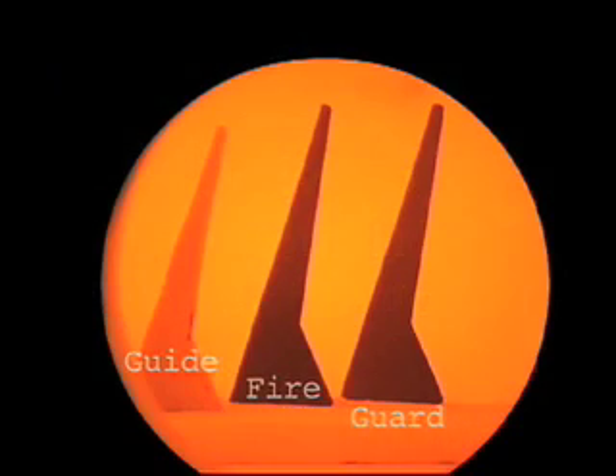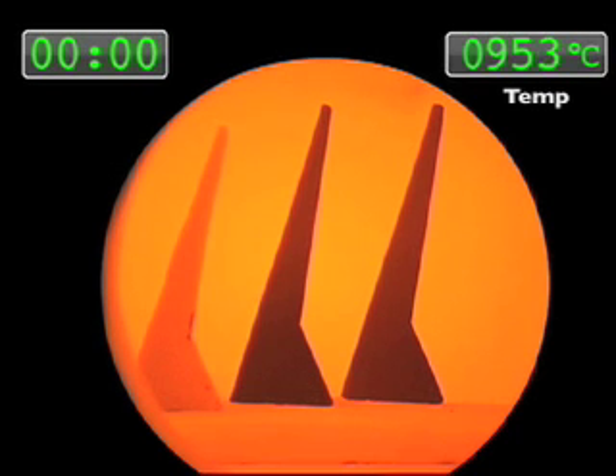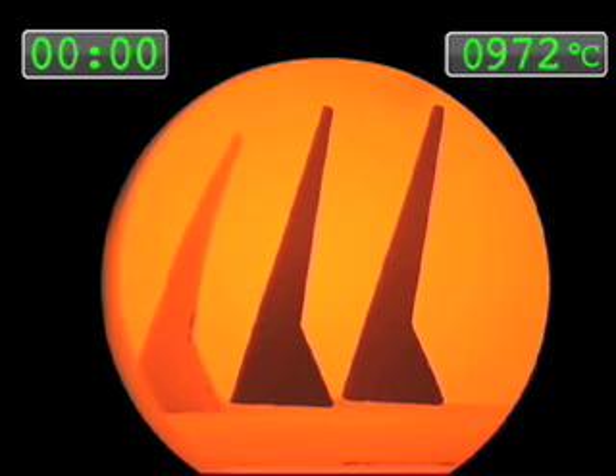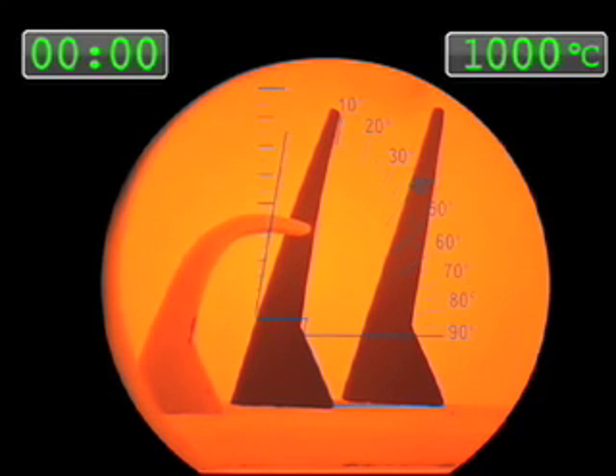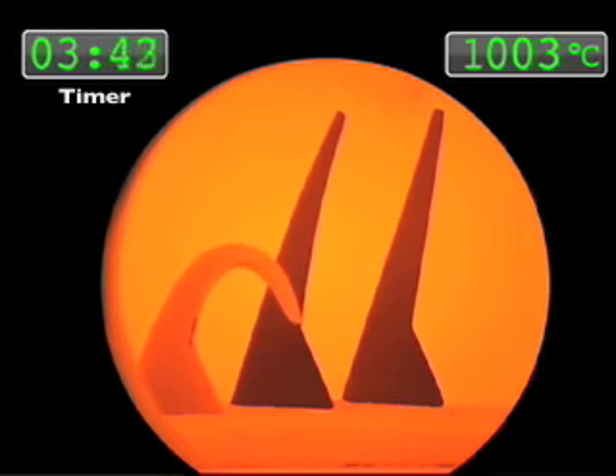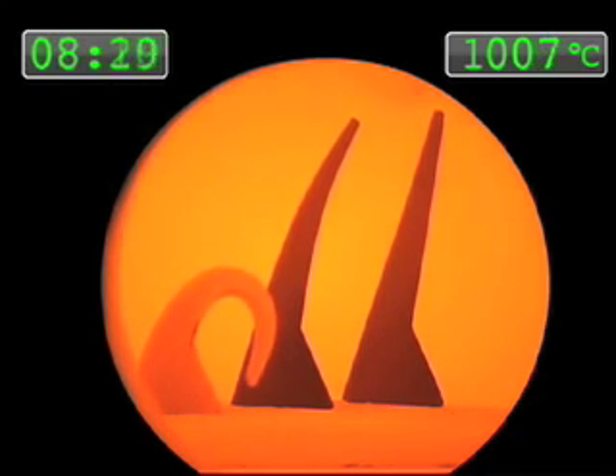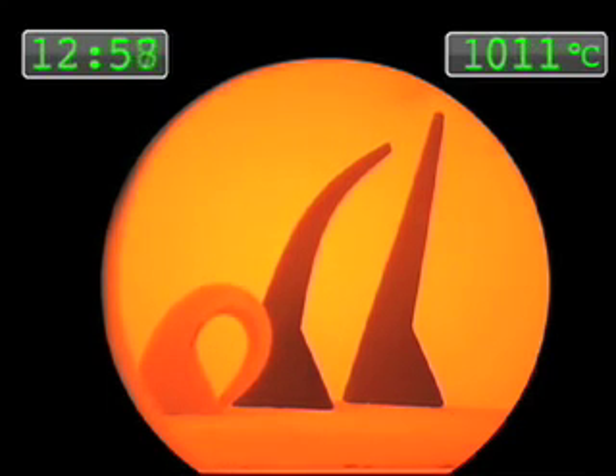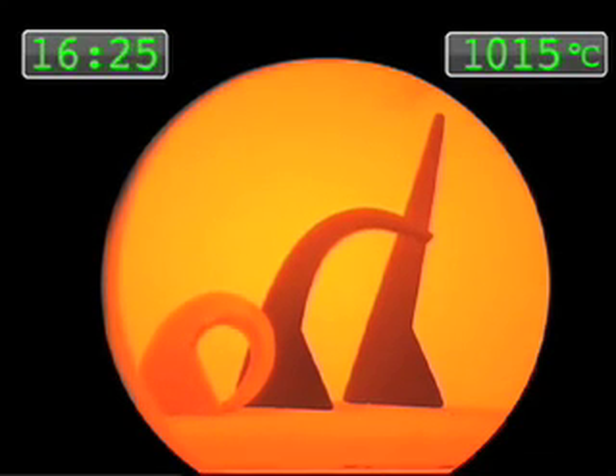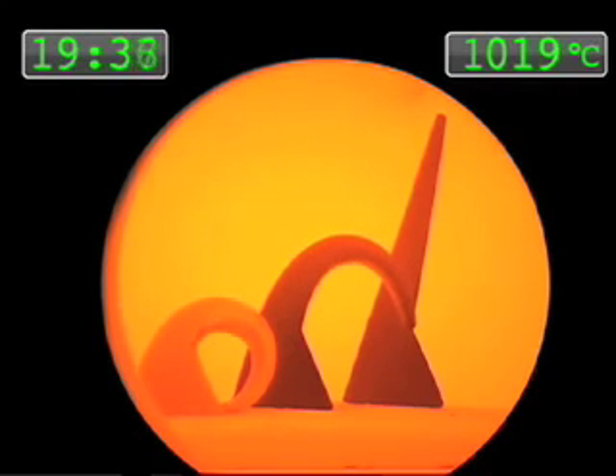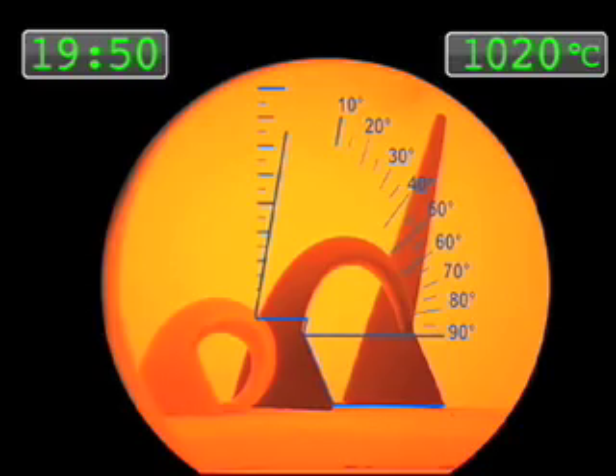As heat is applied to the cone, there are various physical and chemical reactions taking place. When we near the point where the cone can no longer retain its original shape due to the shrinkage or the melting of the cone, it starts to deform. Using pyrometric cones, we start out by having the cone mounted at an 8 angular degree with the vertical. As this melting occurs and the cone loses its ability to retain its original shape, it deforms, typically from the so-called 8 angular degree all the way down to what we refer to as the end point, or a 90 angular degree. The movement then occurs from 8 to 90, or over an 82 angular degree bend.